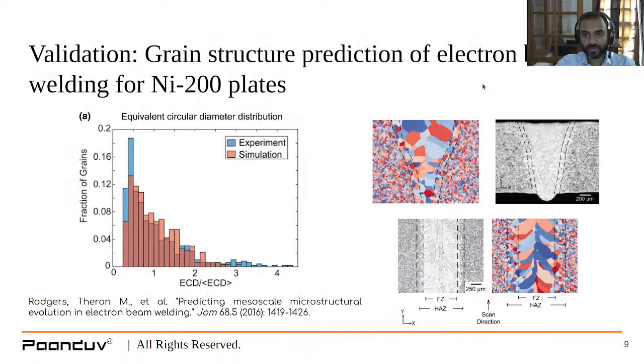Moving on to the microstructural side of things, the validation case study involves grain structure prediction of electron beam welding for nickel 200 plates, and we have 2 images on the right hand side of this slide. The top image is a cross section that is cut through the weld pool, and the bottom image is the laser scan track that we see from top, right? And you can see that the experimental results match very well to the grain size distribution that is predicted by AM PravaH's Monte Carlo simulator. And on the bottom side, if you look at the laser scan track, the results compare very well again to AM PravaH's Monte Carlo simulator.